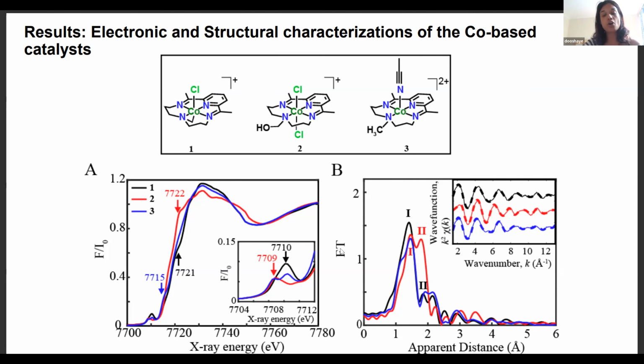The pre-edges of all 3 complexes were also observed at low photon energy, and catalyst 1, with a less symmetrical environment, so less centrosymmetry, has a much more intense pre-edge feature in comparison to catalyst 2. And on the other hand, we observed the typical multiplet feature for the cobalt-2 complex, observed at 7709 and 7710 eV. We also measured the EXAFS of all of these complexes.